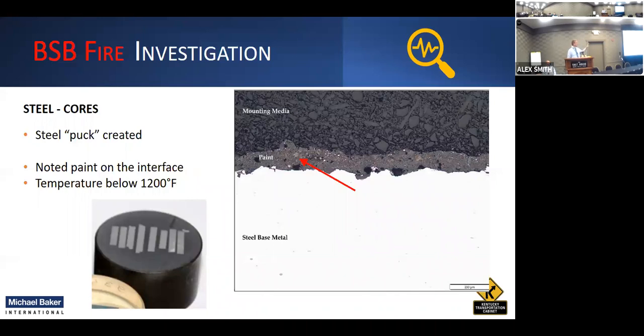So what we did is we took these steel cores and they ended up making a steel puck. So we brought them back down to Louisville. There's a testing facility here. They cut small slivers of that steel out and made a puck that was about 1 inch in diameter.